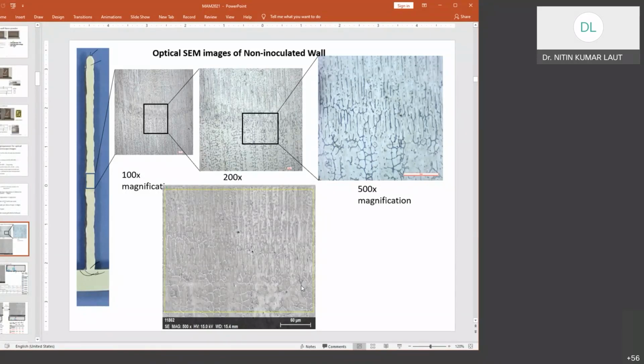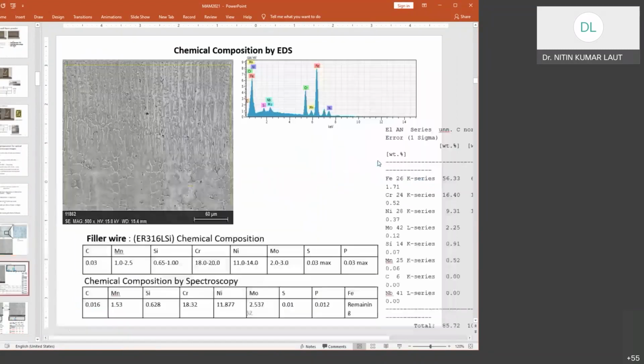Only thing is now we have to see, can we get better grain distribution, or let's say better microstructure than this, although this is also not that bad because we are hardly getting any defects or any problematic things, any foreign inclusion or porosity or any cracking. Okay? So that has not been seen here. So this means that the addition of your powders, specifically nano powders, carries some meaning in the process. So we are still working on that.